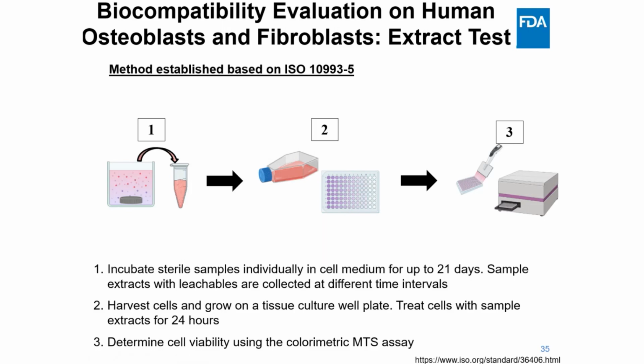So next, to assess the potential leachables from the functionalized surfaces, we perform an extract test based on the same standard, ISO 10993-5. Here, we are using titanium samples coated with gold nanorods, incubated in cell culture medium for up to 21 days, allowing any soluble compounds to leach into the medium. Then these extracts were applied to human osteoblast or fibroblast cells for 24 hours, and cell viability was measured using the same MTS assay described in the previous slide.